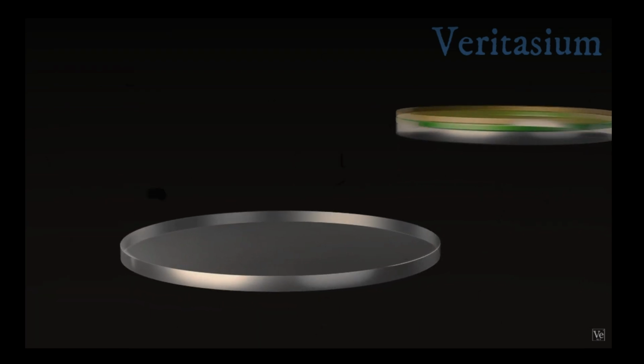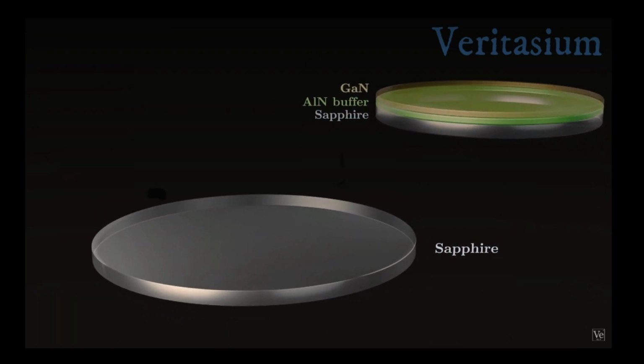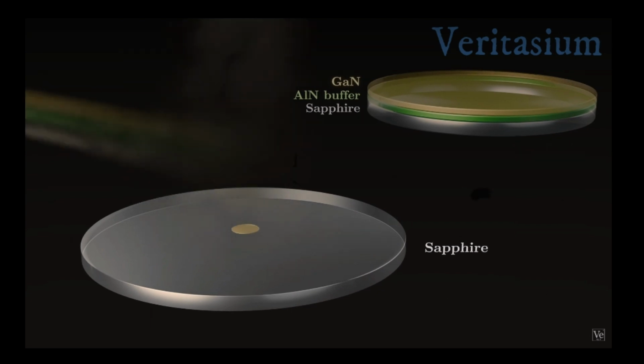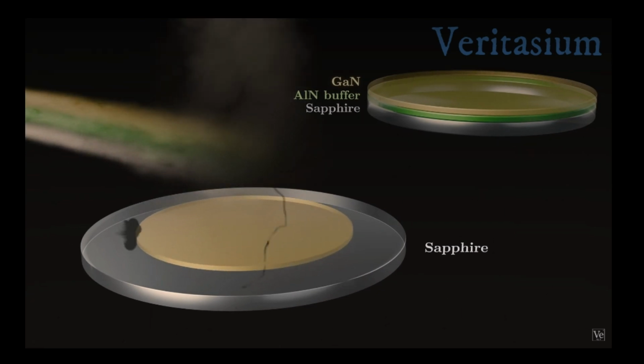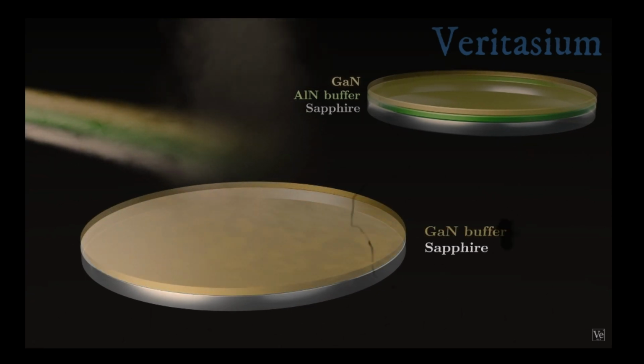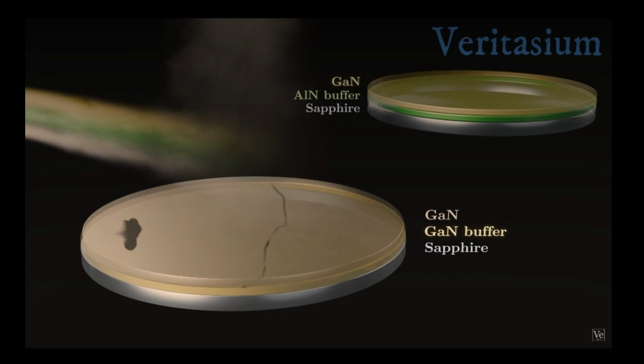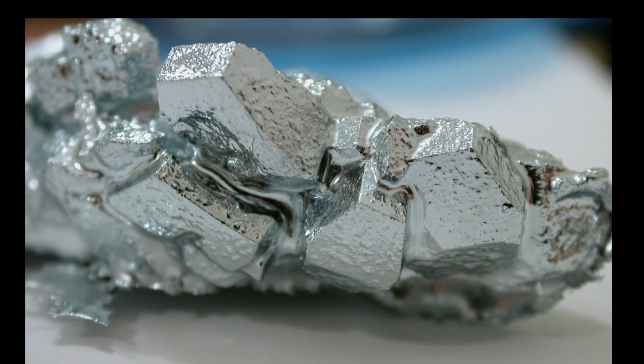Now, he was ready to take on Akasaki and Amano, but instead of copying their aluminum nitride buffer layer, his two-flow design allowed him to make gallium nitride so smooth and stable, it itself could be used as a buffer layer on the sapphire substrate. This in turn yielded an even cleaner crystal of gallium nitride on top, without the issues of aluminum. Nakamura now had the highest quality gallium nitride crystals ever made. But, just as he was getting started, things took a wrong turn.